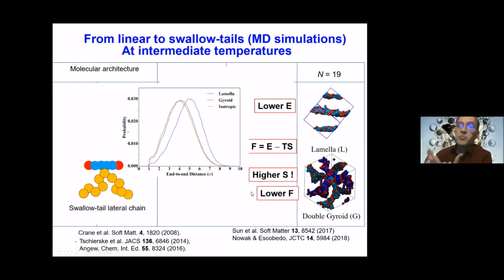So this explains the source of this higher entropy, and also shows you how you can use entropy to create a structure with, in some ways, more order, because this seems to be more order than this. But also you can notice that if I were to change temperature, I can basically kill the contribution of entropy. So at some point, T will be low enough that basically the free energy is dominated by energy. At that point, then the lamellar phase should be more stable. And indeed, that's what is found in simulations and experiments. So I think this example shows you how you can tune the effect of entropy by either the design of the tail or by just changing temperature.